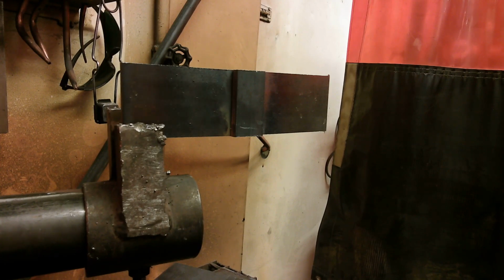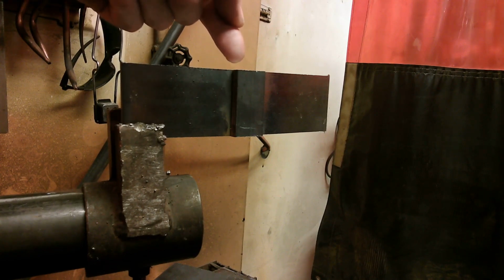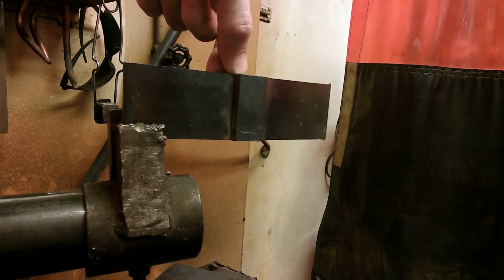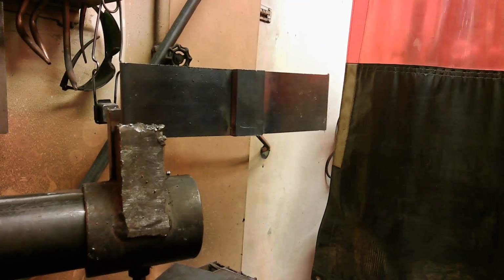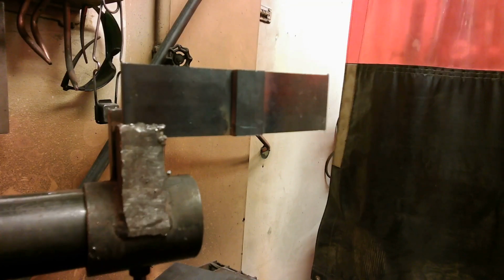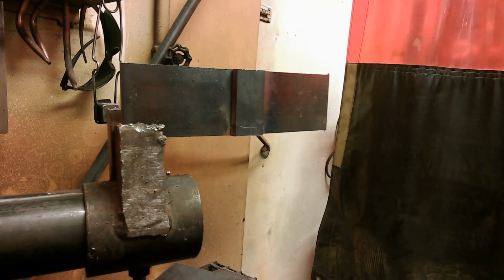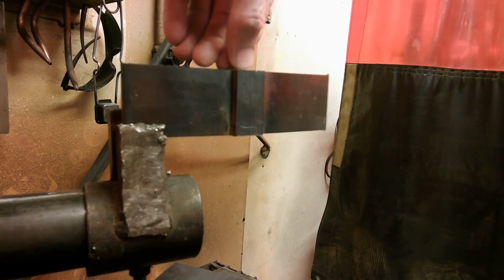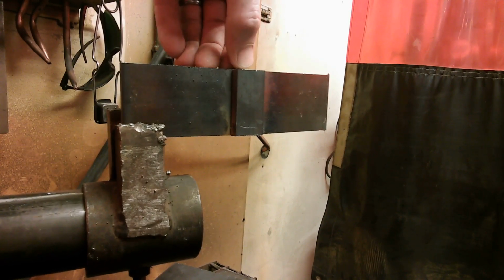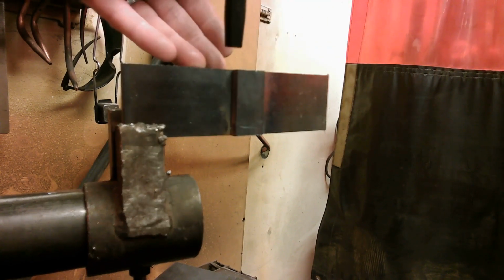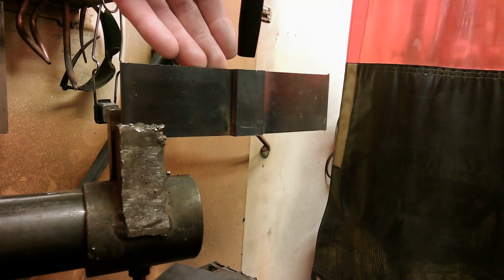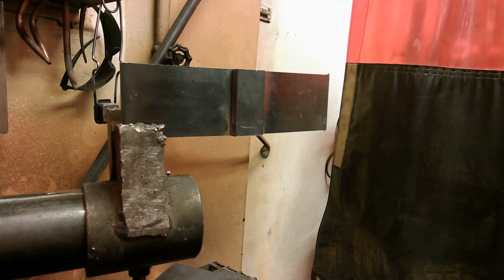So with oxyacetylene, because there's a slight air gap between my backing strip and my base metal, at least on the left side and on the right side, if you accidentally tip the torch towards the base metal, you won't actually cut into it. It's kind of like taking your cutting jet lever, pointing it at metal that isn't preheated and hitting your oxygen jet. You won't cut through it because it's not preheated. That air gap prevents that from happening. The problem is in the center of the backing strip, ideally they weld it into the backing strip and fuse that there. So there's no more air gap, so you do have to be careful as you cross through the center with the torch that you're not angling it back in towards the base metal. Otherwise you will gouge that.